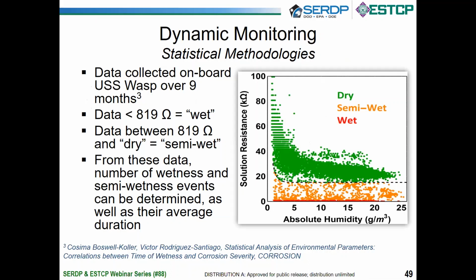So we can take temperature and relative humidity data and calculate absolute humidity. We found that this calculation was a crucial step in terms of finding a strong correlation between the temperature and humidity data along with the solution resistance data.